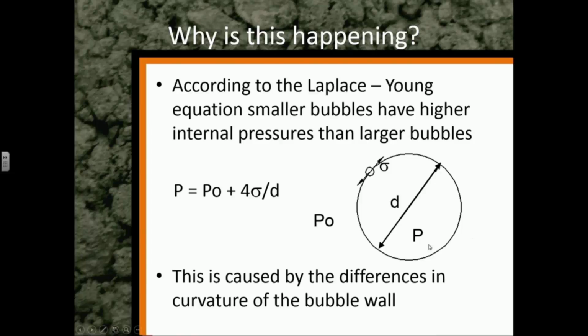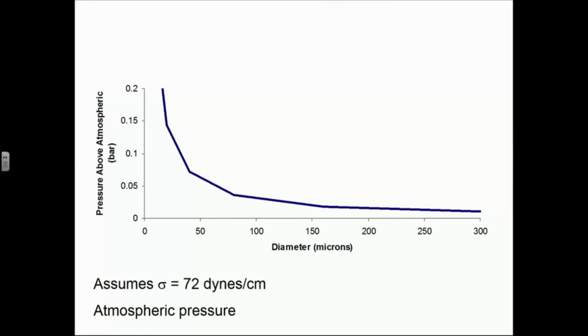It basically says that the pressure P inside a bubble is a function of the fluid pressure around the bubble, the diameter of the bubble, and the surface tension of the bubble wall. Therefore, as the diameter of the bubble gets smaller and smaller, the pressure in the bubble is going to get larger. It's inversely proportional, right? So it shows right there. And here's a plot of that. This just shows that if I have a larger bubble, 300 microns or so, they're going to be much closer to atmospheric pressure than if I have a smaller bubble. The pressure is going to be much, much larger for a given surface tension.